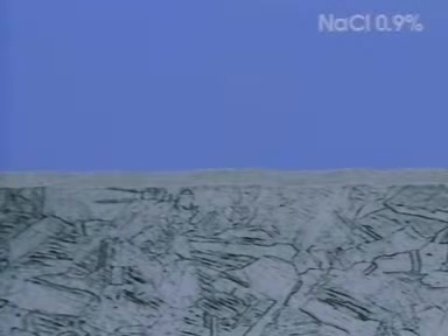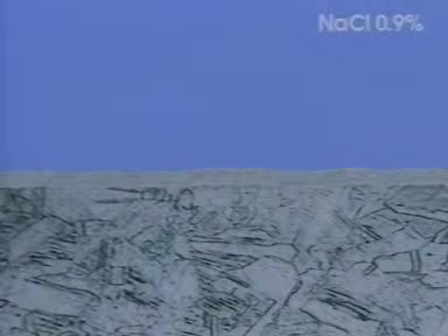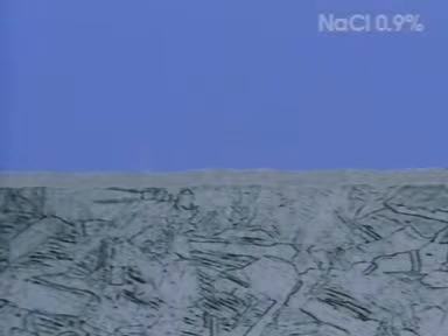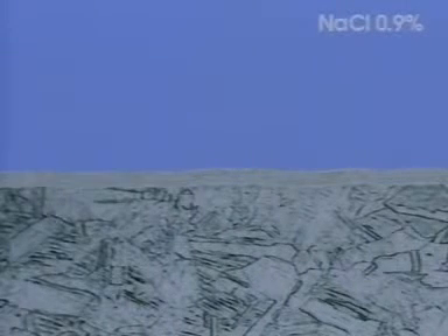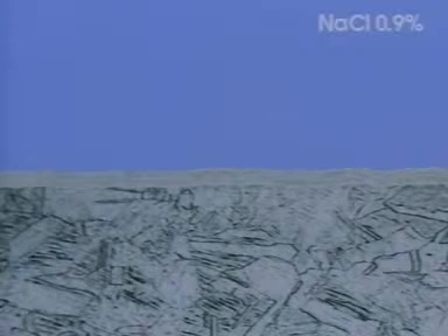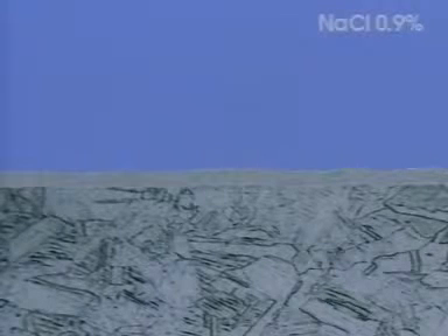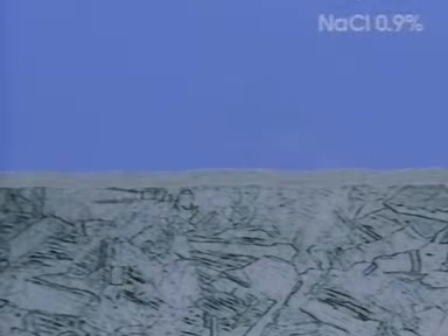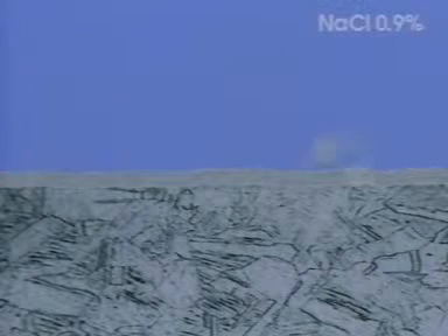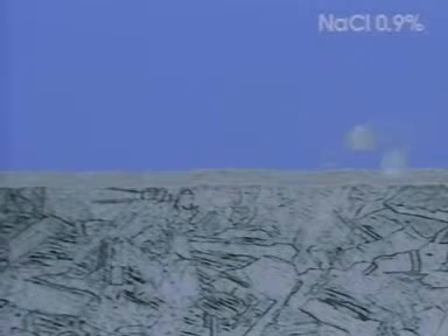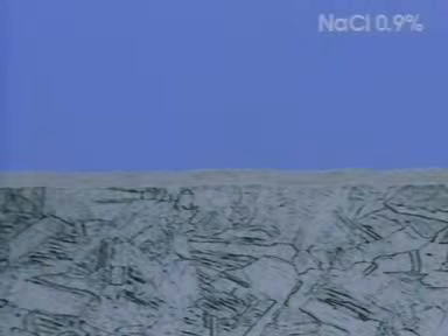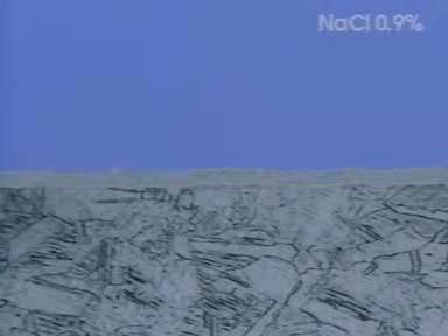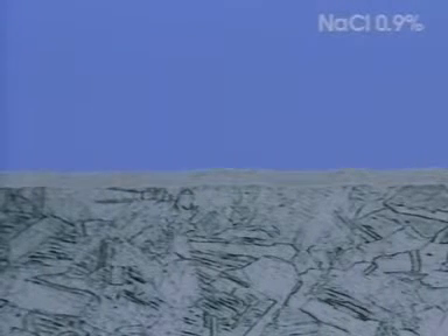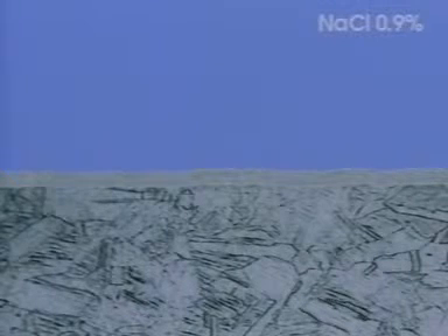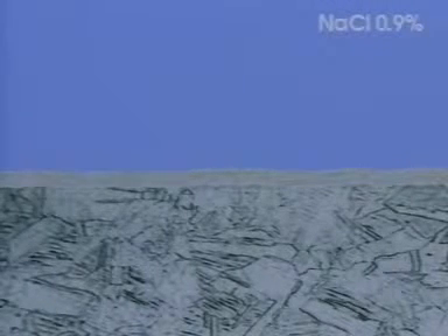Metal ions are produced, and by combining with oxygen, an oxide surface is slowly built up. Both the corrosion and passivation reactions can take place on any surface. On a passivating metal, the oxide formation dominates over the corrosion. We can state that even on fully passivated surfaces, there is a very small but finite corrosion reaction taking place. The passive film is said to be in dynamic equilibrium.